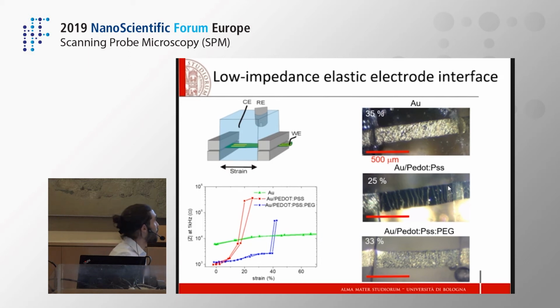In order to keep both the low impedance of the polymer together with a good stretchability, we introduced the PEG, the plasticizer, being able to have an almost constant value of the impedance up to 40% of strain.